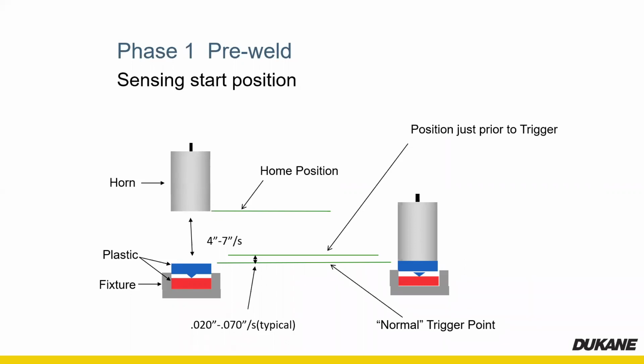With the servo, we drive the horn down very quickly to a point just above where we expect the parts to be. We can make this position very close to the parts if necessary to improve throughput and reduce cycle time, and the more consistent your parts are, the closer we can get in the fixture. I've had sensing start positions as little as 3 or 4 thousandths above where the parts should be, and then we slow down from 4 to 7 inches per second, depending on the press, to 20 to 70 thousandths of an inch per second for our sensing speed.